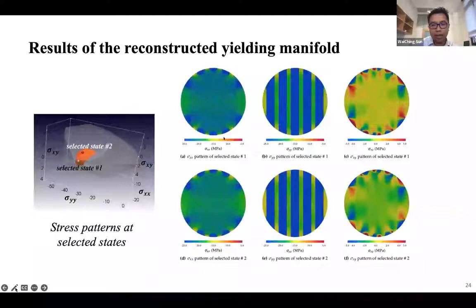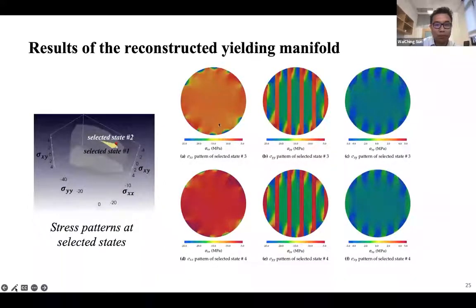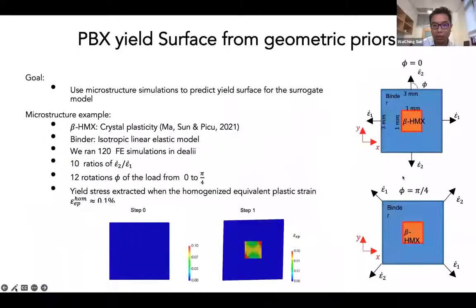And this could be explained by the pattern of the direct numerical simulations in the subscale. What we actually see, which I think is pretty interesting, is that when the two plastic flows are similar, the underlying deformation patterns are quite similar. This is the stress space, loading in slightly different stress combinations on the same yield surface at different locations. And you can also see that when the two yield surfaces are similar, the underlying microstructure deformations are quite similar.